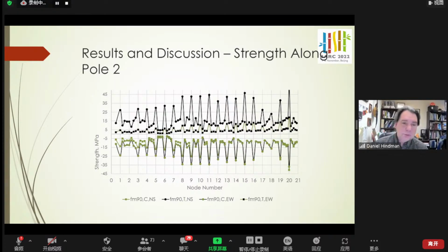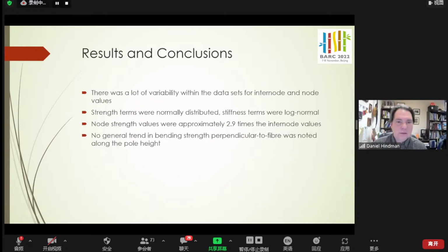So to study the rest of the data for all this variability, we decided to separate the node and internode values into separate groups, and this helped us gain a little more understanding of it. We did see a lot of variability within these data sets, however, the strength terms do appear to be normally distributed, and the stiffness terms were a log normal distribution. Overall, the strength values at the nodes were approximately 2.9 times the strength at the internode.